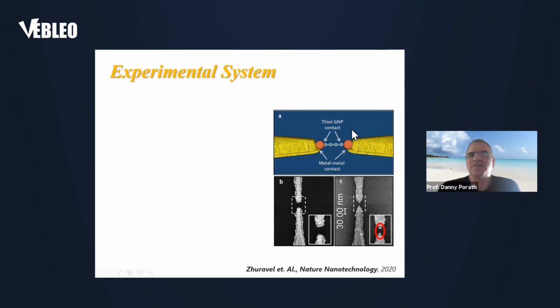The experimental system is shown here. This is the scheme that I showed before. And here you can see a scanning electron microscope image of the electrodes. That's before the trapping, so the electrodes are empty. And after trapping in the way I described before, you can see that a nice dimer is trapped and nicely aligned between the electrodes. And then we could do the experiments.